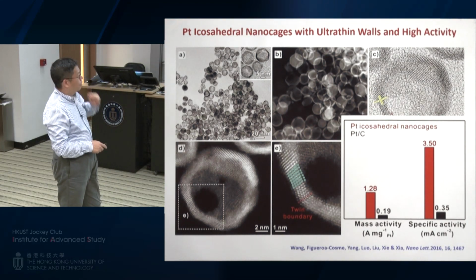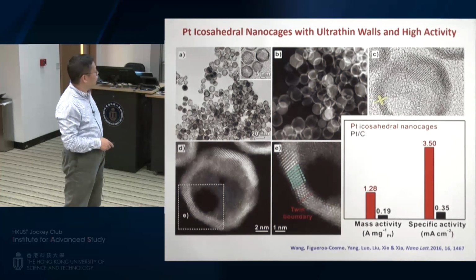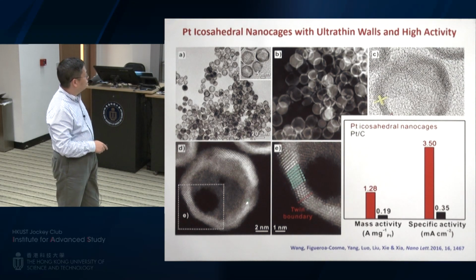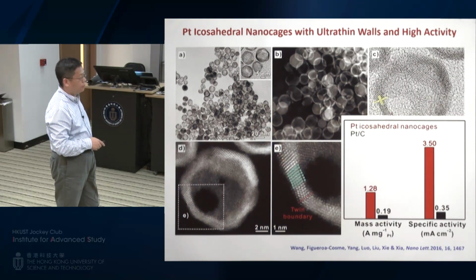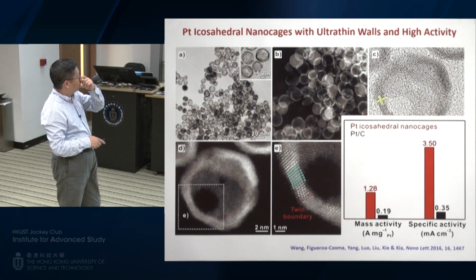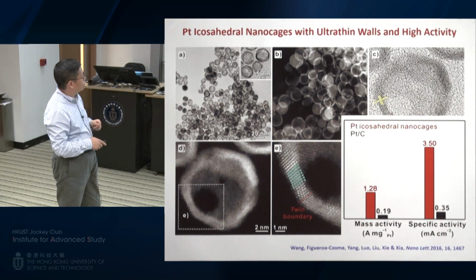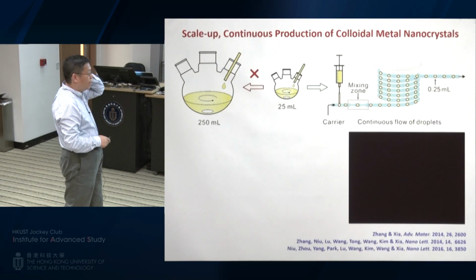Okay, so that's definitely enough. This system also tends to be stable because the structure here is about 18 nanometers across. That's relatively big. That's actually the current focus for us now. We have some collaboration with different companies trying to really push this to the final ideal structure: icosahedral platinum nanocages with only 3 atomic layers for the wall. So that's basically what we are doing.